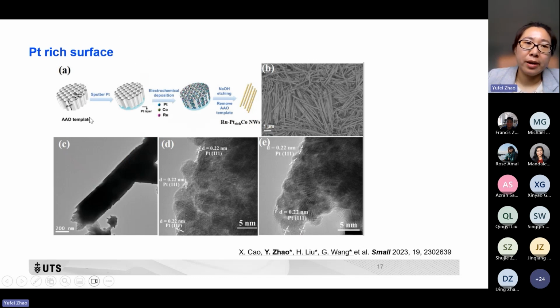So we have utilized this AAO template with the electrochemical deposition method to deposit platinum, cobalt, and ruthenium to form this kind of nanowire structure. Here, the ruthenium content is very low. We incorporate the ruthenium to facilitate water dissociation because we have used this material for alkaline HER. By synthesizing platinum-cobalt alloys with a low amount of ruthenium, we have achieved very good performance. And by high-resolution TEM, we can see the obvious lattice ascribed to platinum. So we assume that the surface may be platinum-rich, with the alloy inside.